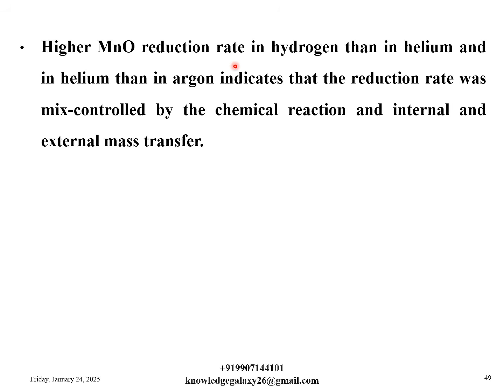Higher MnO reduction rate in hydrogen than in helium and in helium than in argon indicates that the reduction rate was mixed controlled by the chemical reaction and internal and external mass transfer. At high temperature, that is of 1400 degrees Celsius, MnO was reduced in hydrogen and in helium with about the same rate, which was higher than in argon.